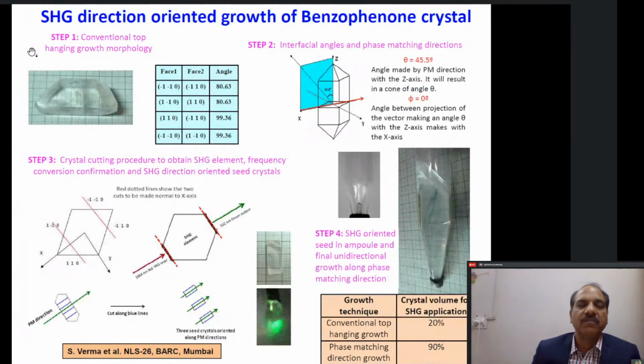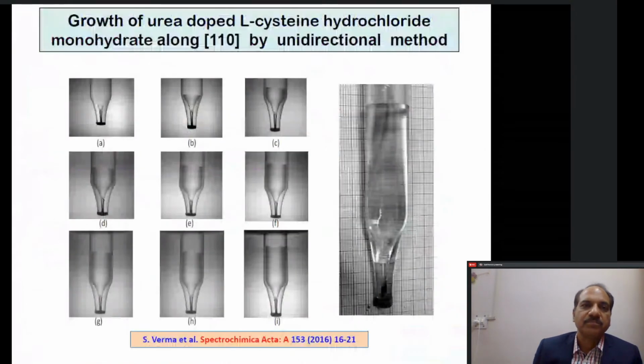in case of benzophenone, if it is a conventional geometry grown crystal, is only 20%. But if you use a phase matching direction seed and put it inside an ampoule, you can increase the usable volume of the grown crystal from 20% to 90%. So this was another example, another way in which we prove that this can be done.